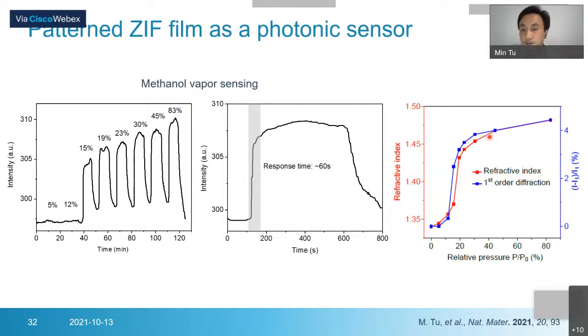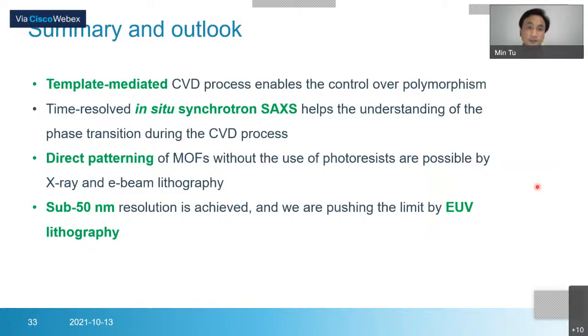The red one is the refractive index we measured by ellipsometry, and the blue one is the relative intensity change of the first order diffraction spot, and it shows a very similar shape. This also confirms that the porosity of the MOF film changed after patterning. So, coming to the summary.